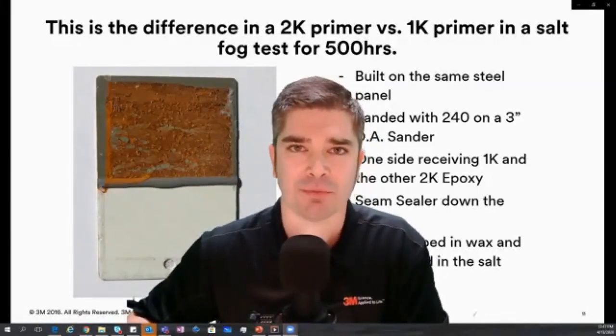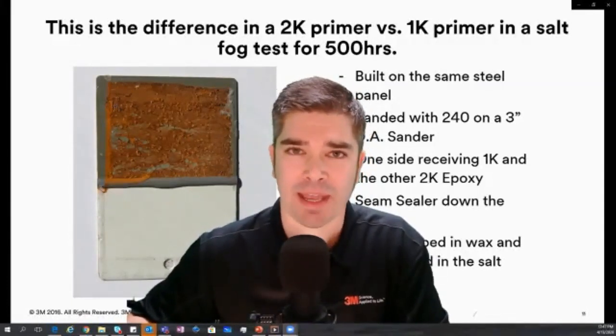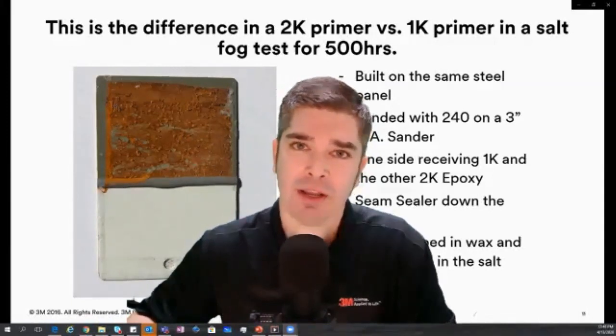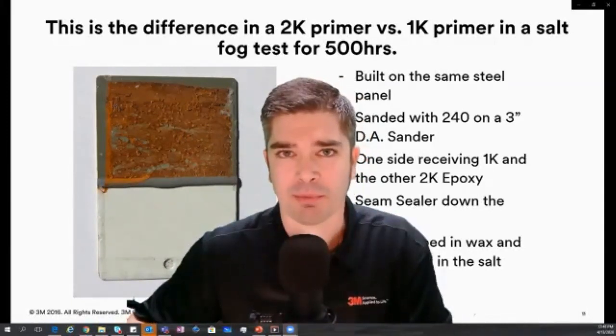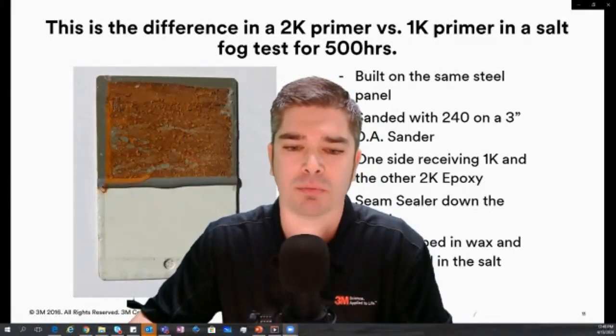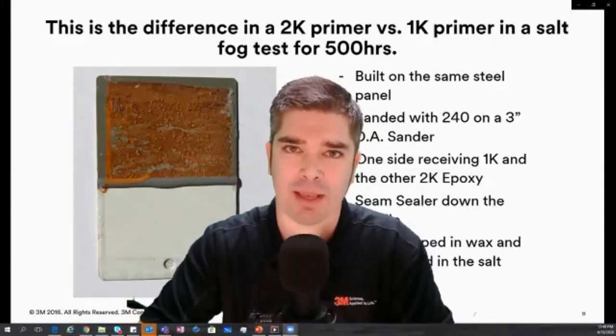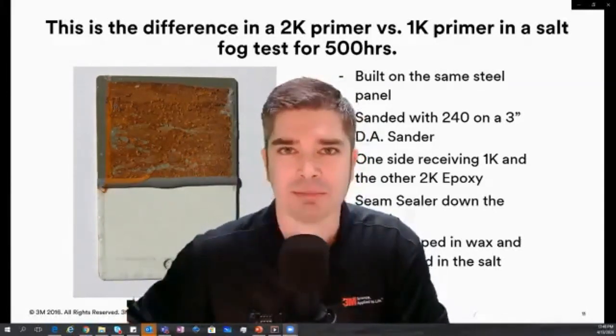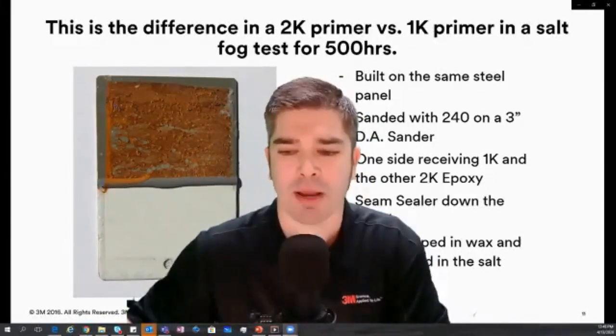And a lot of times we see guys that will put down the acid etch and then the seam sealer and then put the urethane primer over the top of it. And we want to avoid that as well, because we have two dissimilar chemistries working together there in the seam sealer and the etching primers. So we always want to avoid etching primers at all costs.